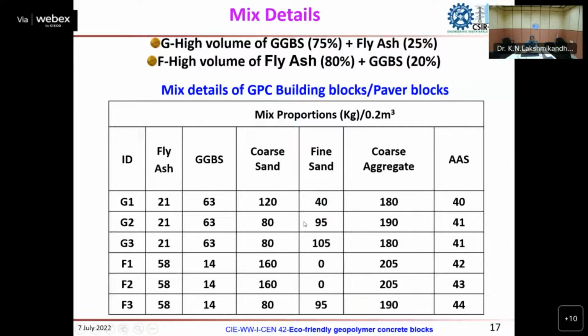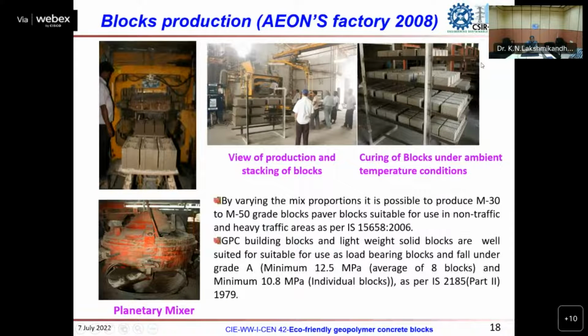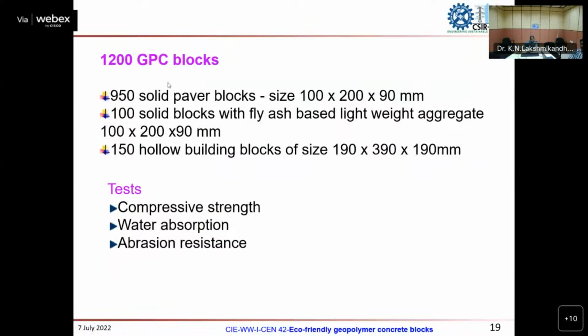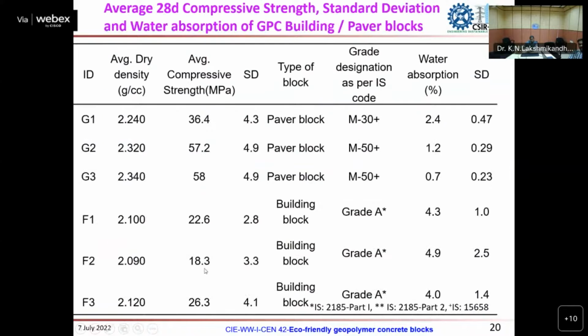And there are two different high volume fly ash and GGBS based mixes. We arrived at them in the laboratory after several trials, and different grades of concrete have been developed. This is a production view of the hollow blocks and solid blocks and stacking for ambient curing. And all the characterization and properties were determined with respect to the IS codes for cement-based systems, which we utilized at that time. About 1,200 blocks we have produced for one trial batch, consisting of solid blocks and hollow blocks. And these are the properties also.